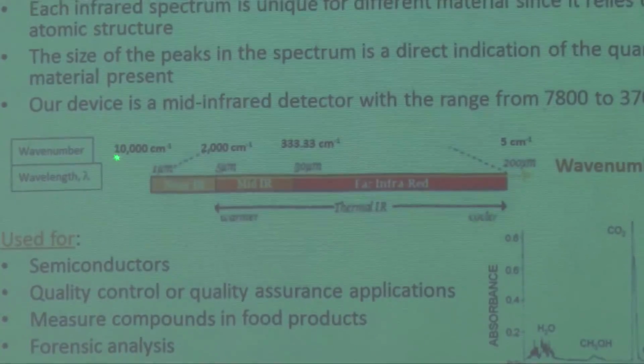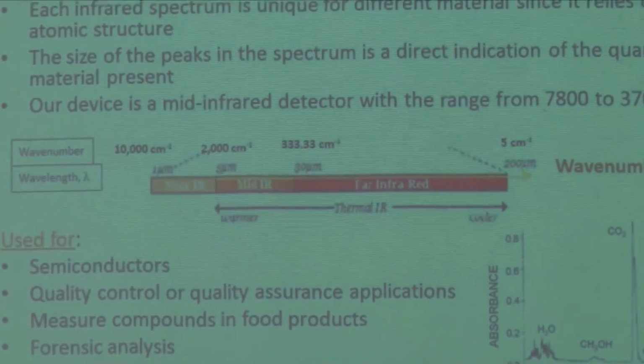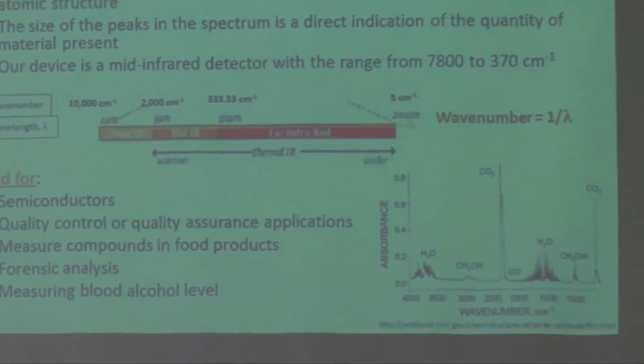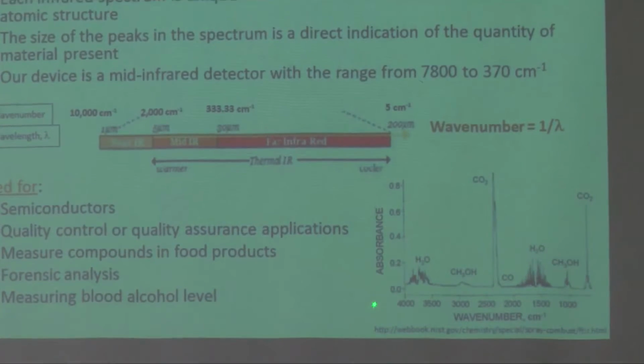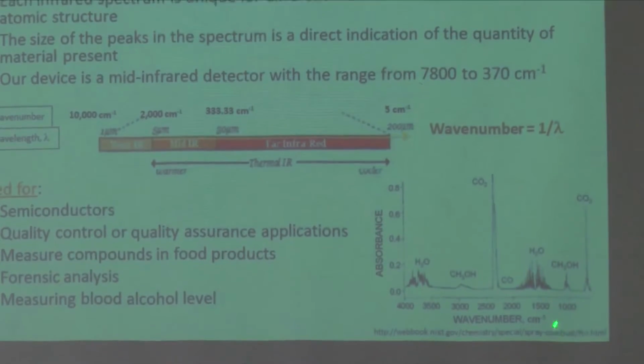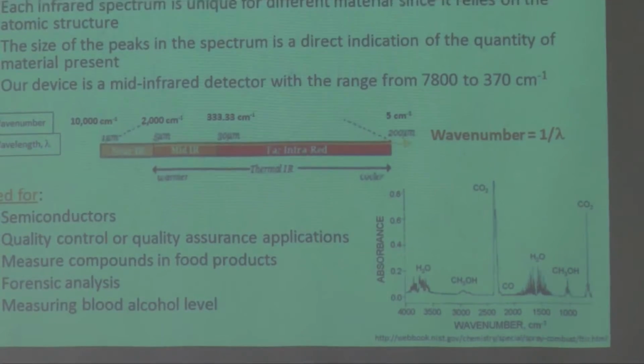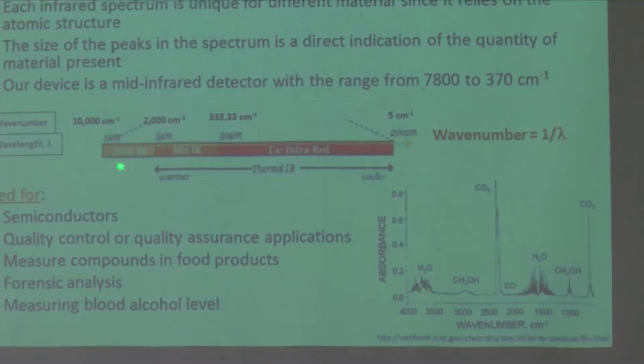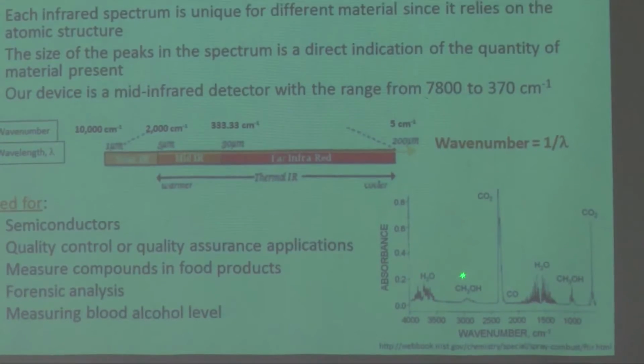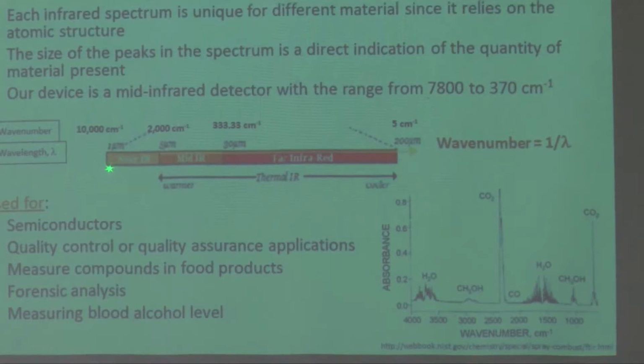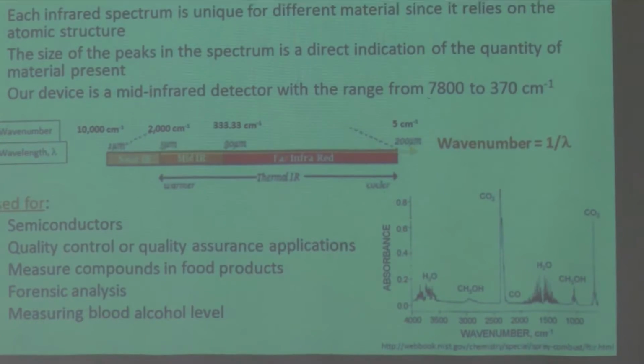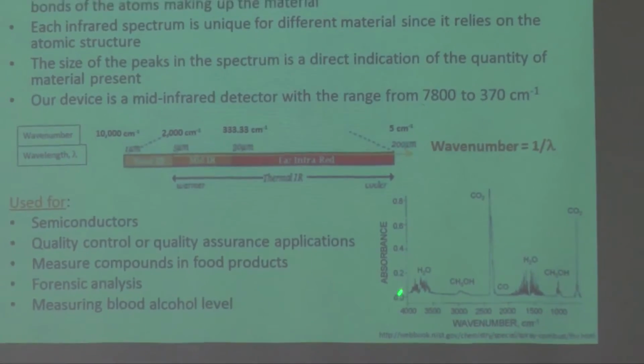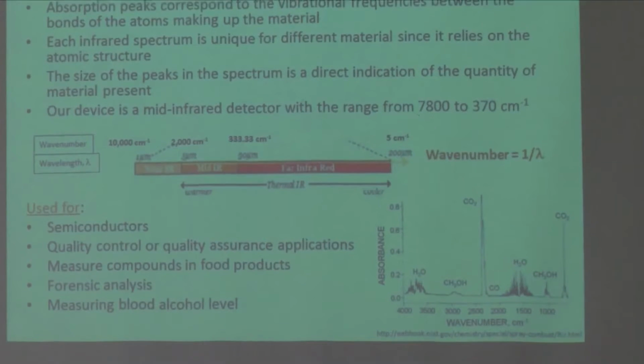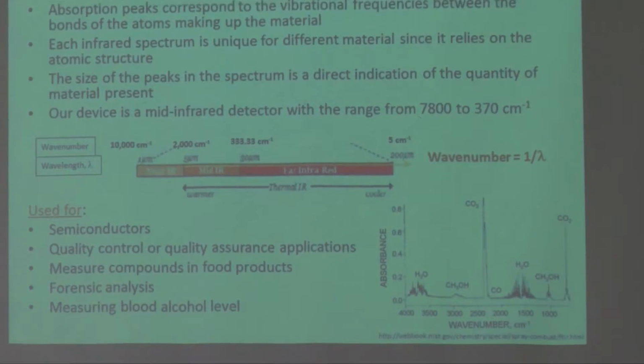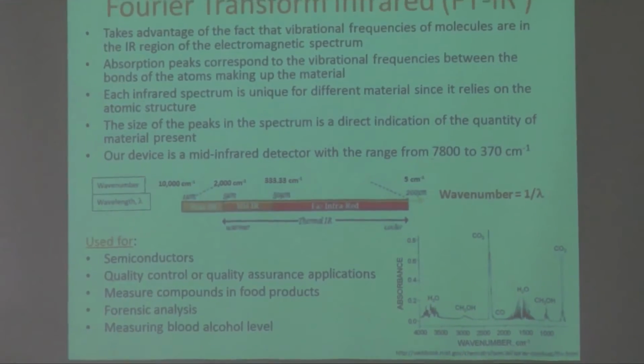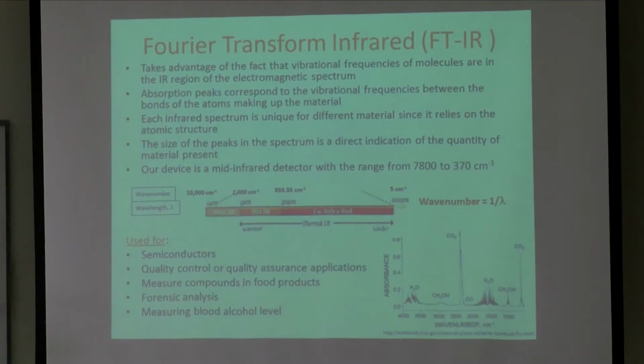The reason why I put the wave number up here is so you can see what range this device was taking a look at. Since this is between 4,000 and 1,000 inverse centimeters, it's taking a look at maybe this region here. I got this off of the internet, and the device that was taking this spectra was utilized in the near infrared and the mid infrared. Our device only takes a look at the mid infrared. The peaks determine what type of material is in the sample. And of course, the size of the peak gives you an indication of how much of that material is inside. So this is really utilized for many things.